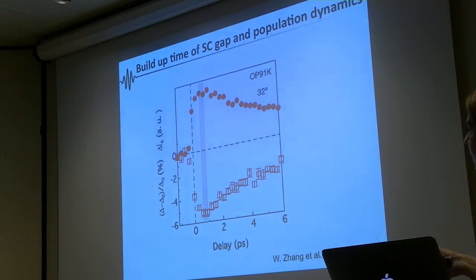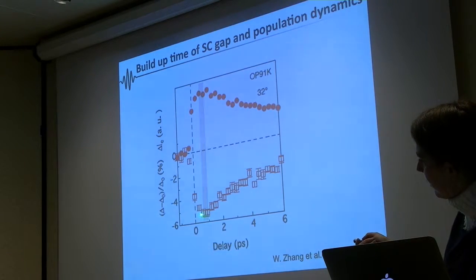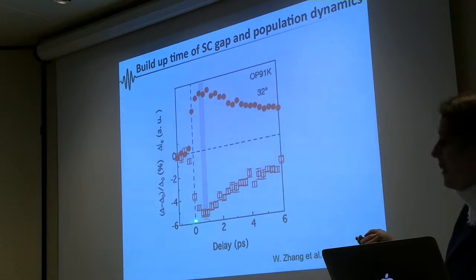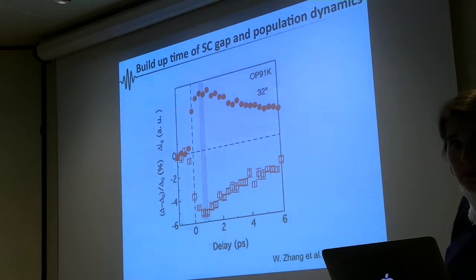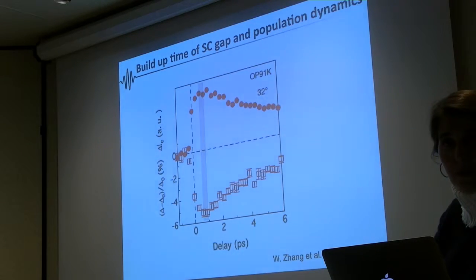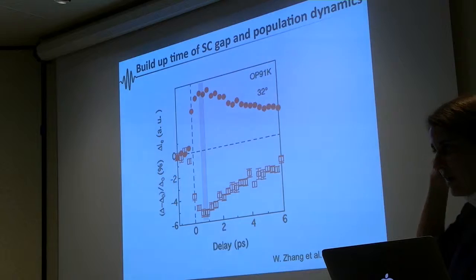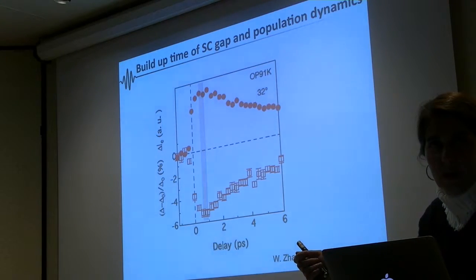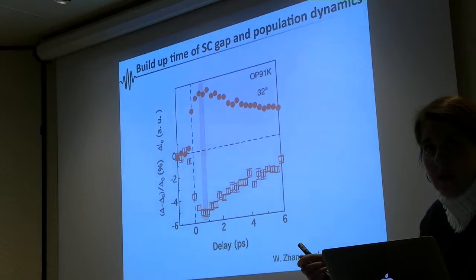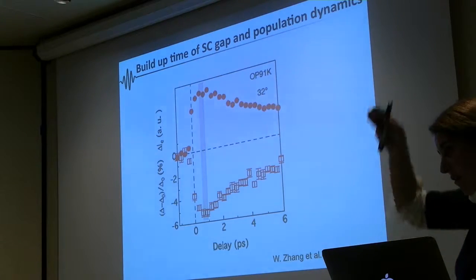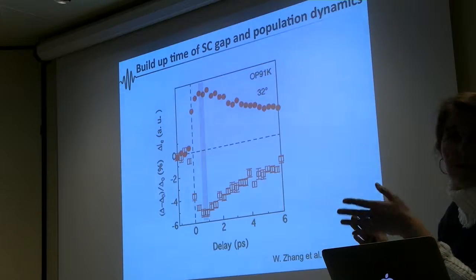And so now we do the same exercise we did before. We are looking at this gap minimum. Now I'm again zooming in close to t equals 0. When we zoom in close to t equals 0, we see something similar: the gap doesn't respond right away, but there is a delay in the response of the gap. And this is true at any fluence we used, up to a certain point, which I'm going to show you in a moment. So I come in with up to like 15 microjoule, and 50 microjoule is actually the point where my fluence curve will go to 0. So I'm completely closing the gap.